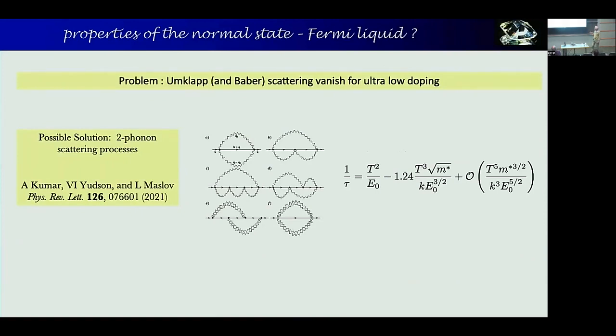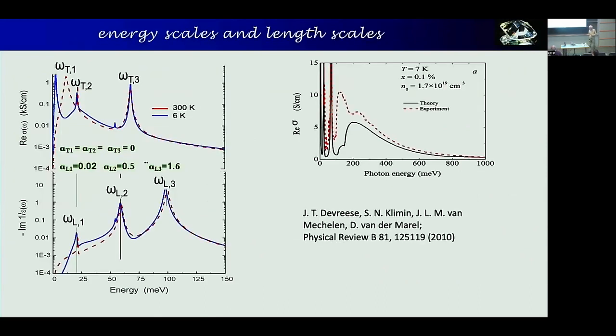So a possible solution that was proposed by our chairman of this session and his collaborators is that you actually have 2 phonon scattering processes. They solved these diagrams. It's a subset of these diagrams that went to this formula over here, but indeed the dominating term is T square, and that has to do with just the electrons shaking off two phonons at the same time. There are relativistic effects at play here.